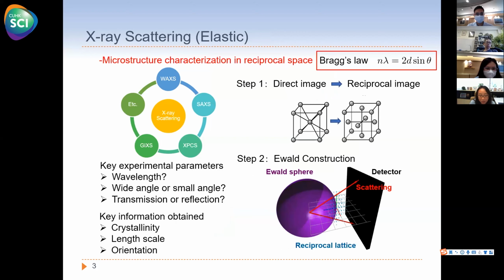There are a lot of different variants of X-ray scattering, but the basic principles are very simple. They are all based on Bragg's law. Basically, it tells us the length scale of the structural order that we are interested in is related to the wavelength of the probing beam and the scattering angle. If we want to visualize the scattering pattern, we have to go to reciprocal space, and then we draw an Ewald sphere. The reciprocal lattice points intercepted by the surface of the Ewald sphere will satisfy Bragg's law, become constructive interference, and become bright spots projected on our detector.